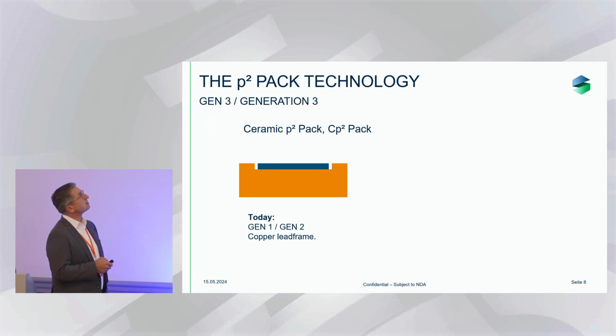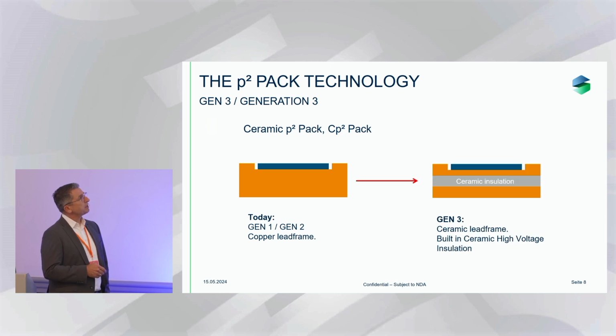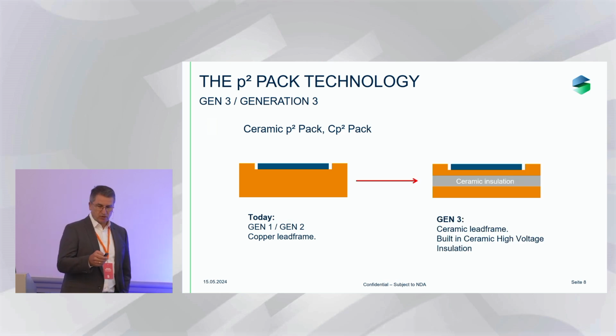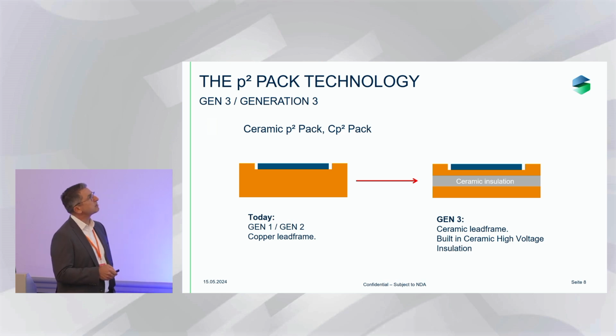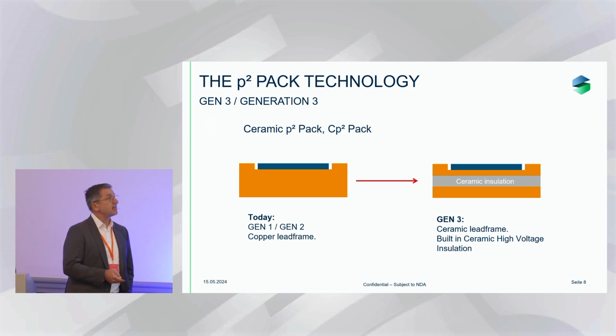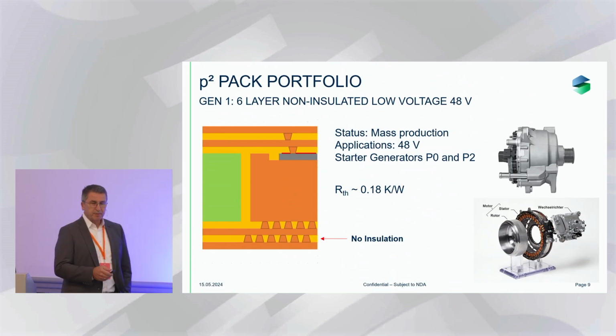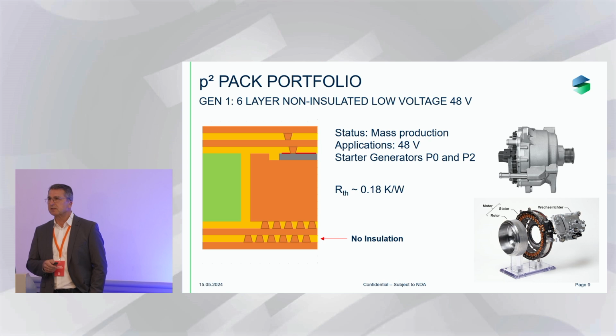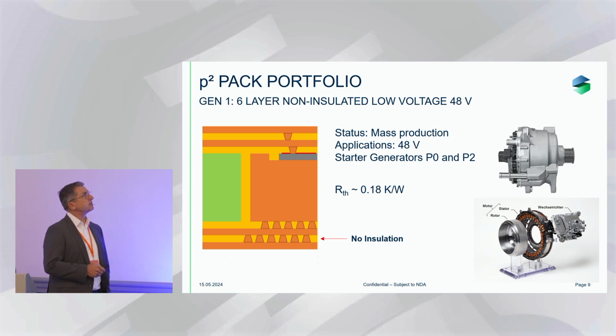And now we talk about the generation 3, which is actually a ceramic P-square pack, or in short terms, CP square pack. Today in the generation 1 and 2, we use just a copper lead frame. That means it's just a copper block, massive, with a cavity, and the power semiconductor is inside the cavity. And this will be replaced by a ceramic substrate. Also a ceramic substrate with heavy copper layers on the top side and at the bottom side. So at the top side, we also create this cavity, bring in the die. So from the outline, it's pretty similar to this one, but the ceramic insulation is already in the level of the standard cell. And as the ceramic has got a much higher thermal conductivity, the thermal resistance will drop tremendously, which I will point out with the next slides.